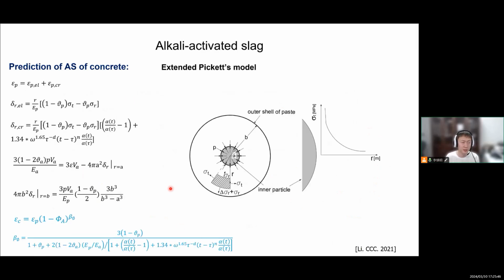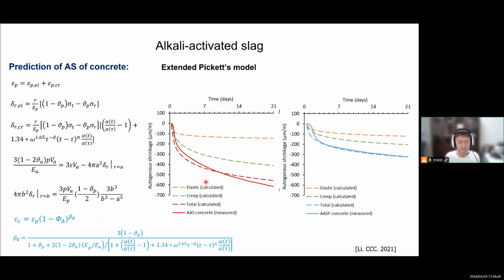So we consider this creep part in the equations, and we integrate the creep part into the equations. We calculate the force between aggregates and the paste. But there is, of course, a limitation. We assume the paste is very large, and the aggregates do not really interfere with each other. But we agree that in reality, the distance between aggregates is actually not that large. It's actually small. So aggregates will influence each other. So this is just the initial model. We assume the paste is very large, and then we integrate the creep part into the model, and then we calculate the shrinkage of concrete based on the shrinkage of paste.